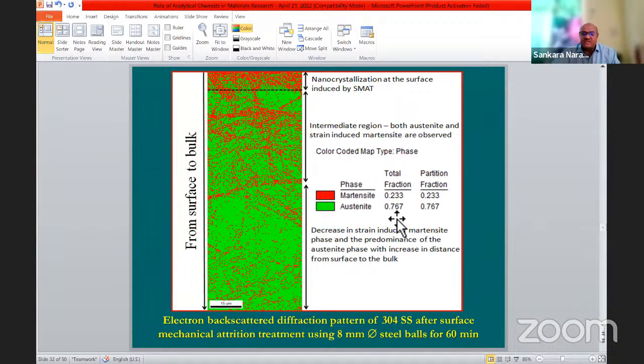Initially before treatment, it will be totally 1. It will be completely austenite phase. But after treatment, about 24% of martensite is formed. So depending on the condition, you can vary it. This is for 8 mm dia ball for 60 minutes.